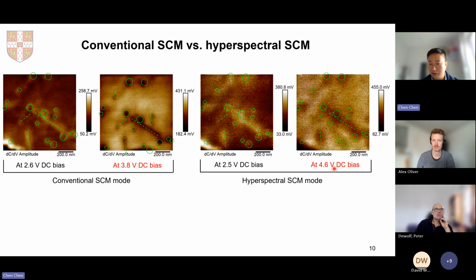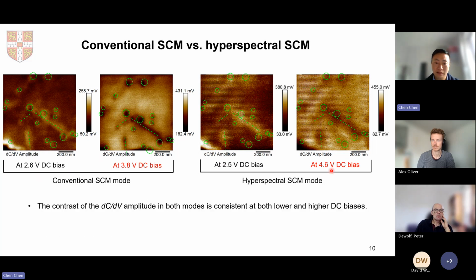Similarly, we collected a slice at a higher DC bias, 4.6 volts, and the features show dark contrast. So the contrast in both modes is consistent at both lower and higher DC biases. Overall, we can see that the hyperspectral SCM data are quite reliable.